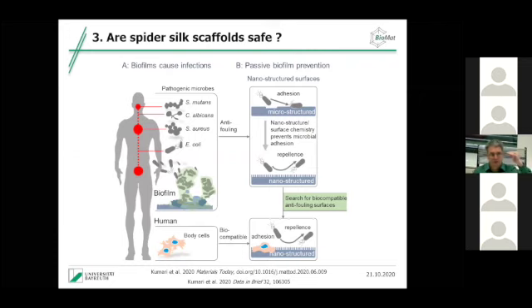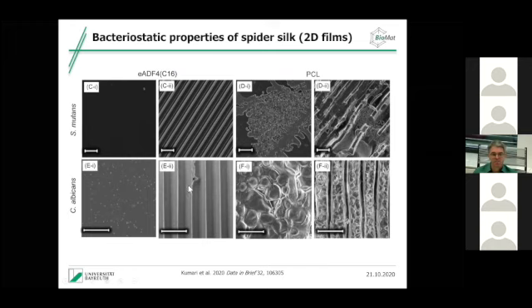If we generate a nanostructured surface, we would like to have bioselectivity. We would like to have the body cells growing on top, but at the same time having the bacterial repellency. And this was something that we investigated, though the whole study took 8 years, no kidding, 8 years to get the results, what we can do with spider silk. And here you see, again, our workhorse, our negatively charged silk, flat films and structured films, because we wanted to find out whenever we have surface topography, if this might actually accelerate or support bacterial growth.